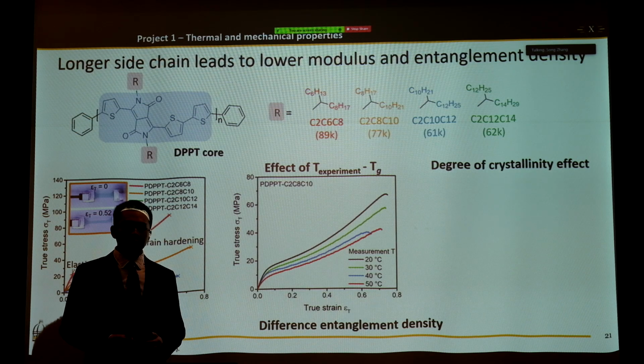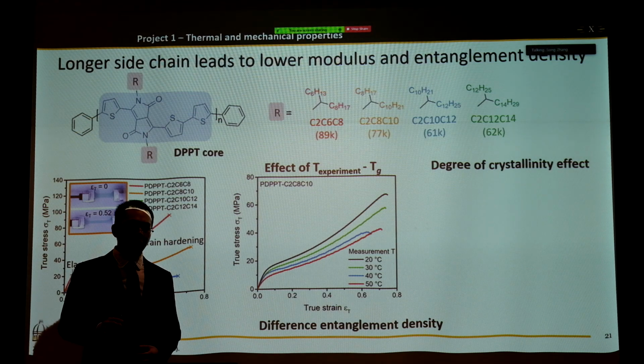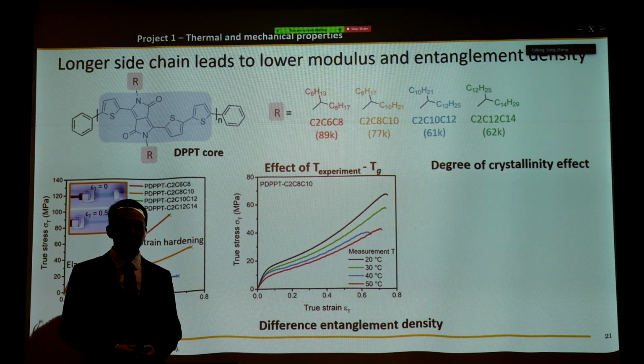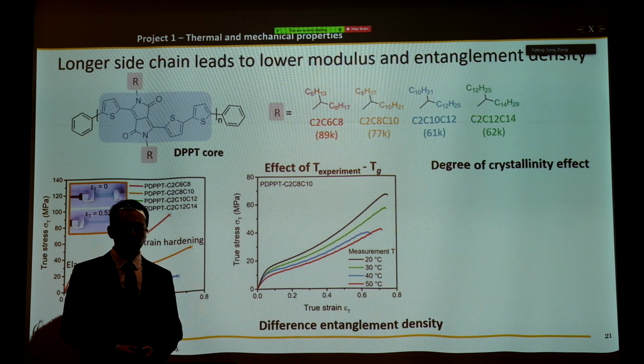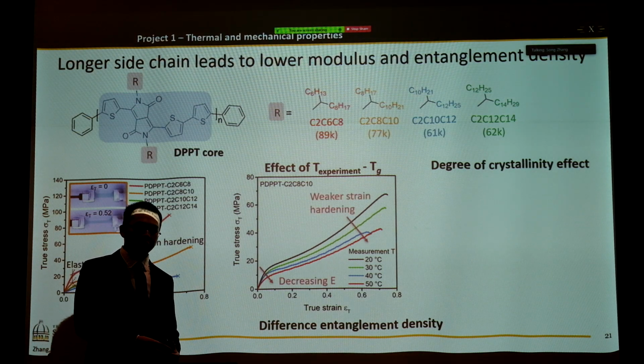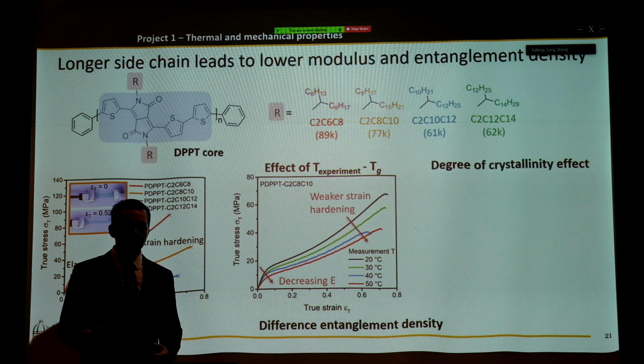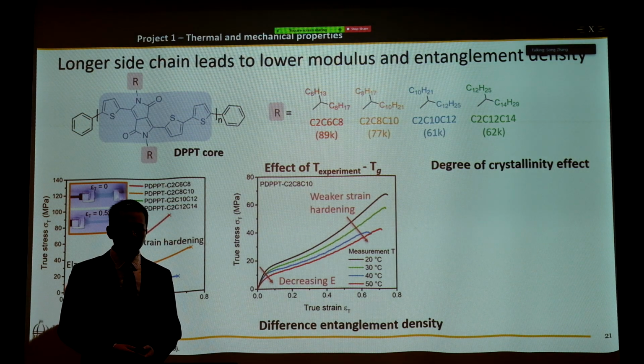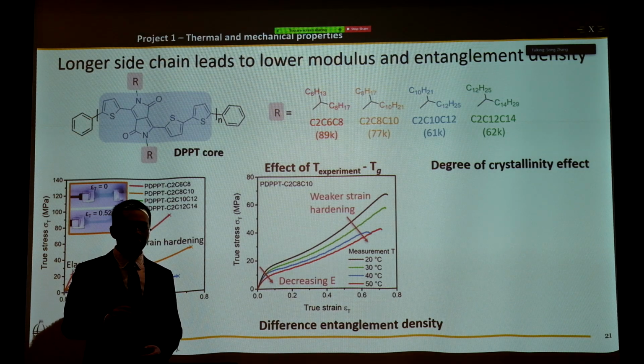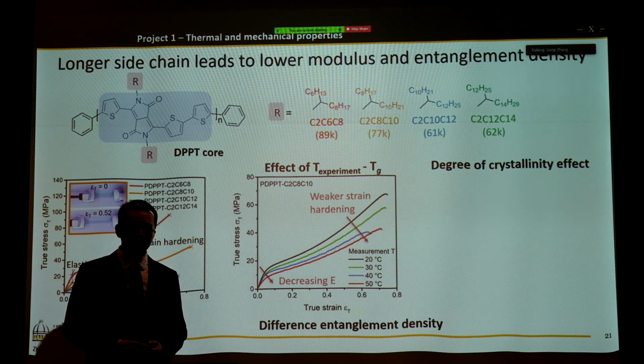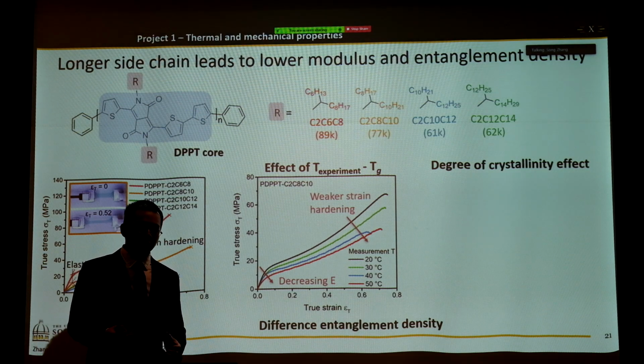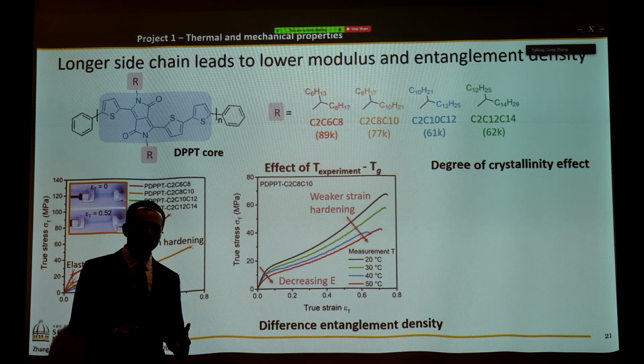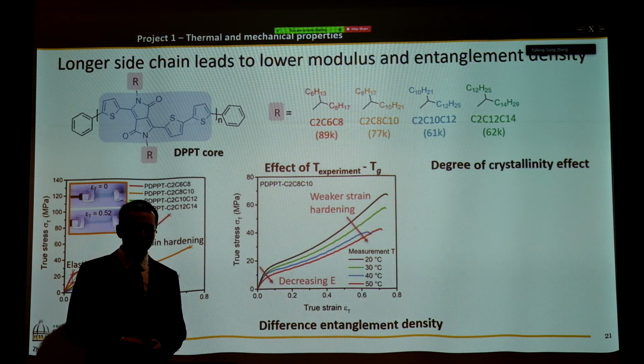Okay, let's take a look at the effect of T minus Tg. We can simply warm up the water bath and perform the tensile test at different temperatures, from 20 all the way to 50 Celsius degrees. And we saw an evident decrease of elastic modulus with increasing experimental temperature, which is expected. In the meantime, the strain hardening behavior is becoming weaker and weaker. So the temperature does play a very important role here. However, it turns out the slope change here is not as severe as we saw in the curve on the left, because for the longer side chain length, it seems like it's almost flat at higher strain.